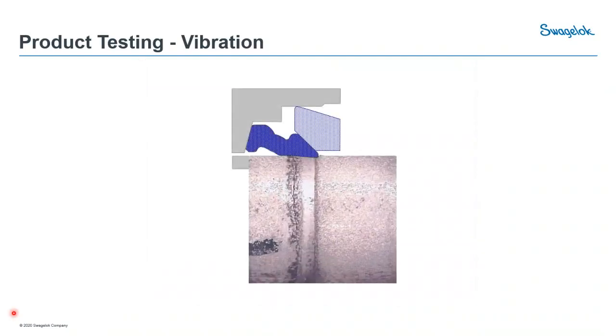But really what's happening when we take that vibration, millions and millions of cycles, and we take it to that form of failure, really how does it fail? Now, if you think about tube fittings, often you'll have the stress riser on the front of that ferrule. So in some tube fittings, that's really where you'll see that stress riser. You'll have a very small point of contact here on the tip, and that's where you might expect fracture. But when you look at a Swagelok tube fitting, you actually see fracture further back on the tubing.